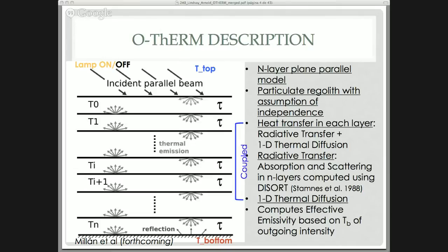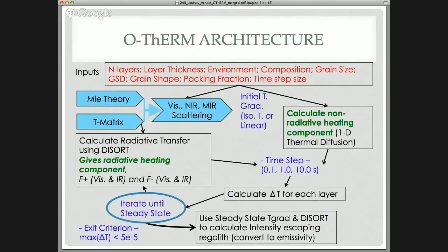So we input the number of layers that DISORT is going to use. This is typically 100 to 1,000. You have to determine how thick each layer will be. You have to define the environment. Is it an airless environment? What kind of temperatures are you going to be using? What is your input composition? Right now we're limited to a single composition, but that's very useful for comparisons to laboratory measurements that Neil was just talking about. Then grain size or grain size distribution. And to answer Paul's question briefly, but not in detail, you can input grain shape information and packing fraction, and then you have to select a time step size.